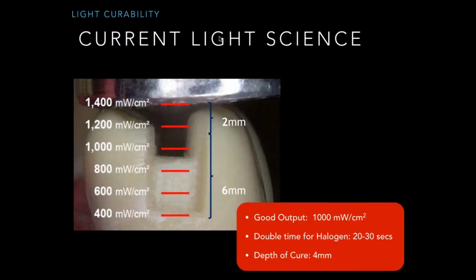I'm going to show you a little bit here how some of that value can change, but there's a lot of ways this can be affected, and maybe that 4 millimeters is really not as true as what you would think. And when I look at this line here that's going to come across here, this is a 4 millimeter level increment, so you need to really consider how your light is affecting the depth of cure, the base of that proximal box. You need to understand what could be above that. Is there a ring? Is there a matrix on a Class 2? So there's a lot of components to really consider. Also, if you're using a halogen light, make sure that you double the time for curing.